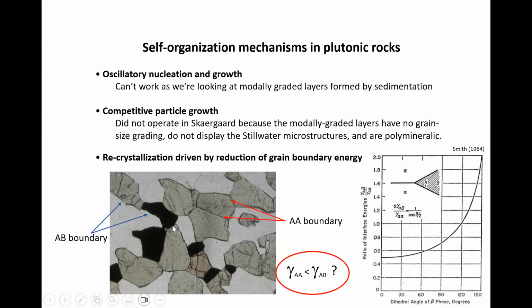So if that's the case, and the rock has got enough time to sort of mull over its past misdemeanors, what it's going to do is recrystallize so that you end up with monomineralic bands, because by achieving that, it reduces its overall energy. Okay, so it's based on this premise that the AA grain boundaries have got a lower energy than AB grain boundaries. Now, there's a very, very easy way to test that, and that's because the geometry of 3 grain junctions is governed by the ratio of these 2 things.